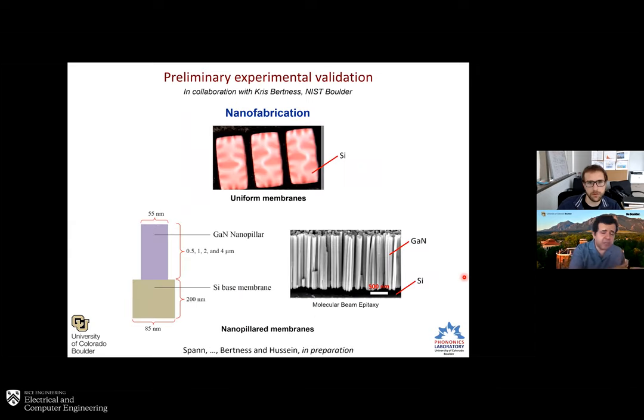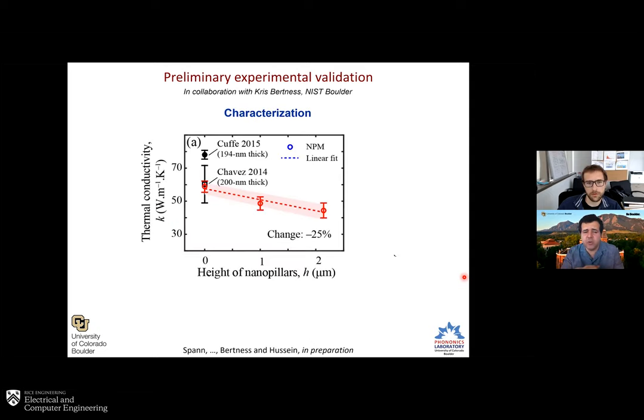And then on another parallel track, with my colleague Kris Bertness from NIST next door here in Boulder, we've been fabricating some structures. This is gallium nitride grown on silicon membranes using molecular beam epitaxy. We have some preliminary results there as well, showing that the thermal conductivity, as we predict, is going down with increase in nanopillar height. Now, the reduction here is 25 percent only, but that's because we didn't attempt to optimize that system. This was just a proof of concept.